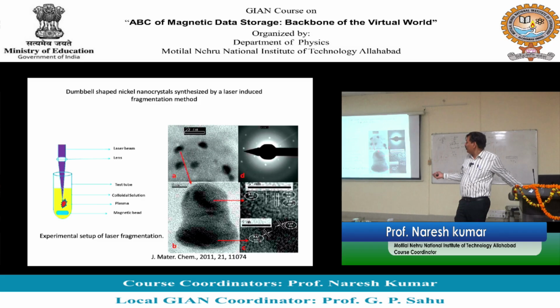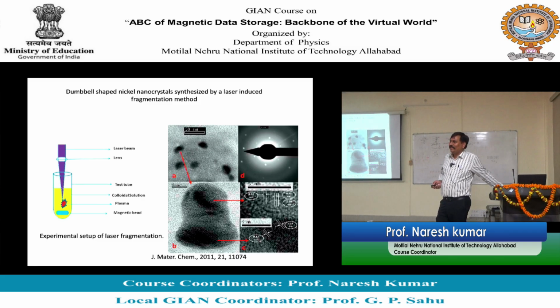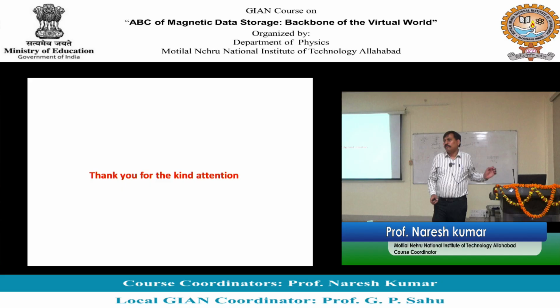But this looks easier than it is. We had a big, just an accident, I would say. The moment you shine light here, it will catch fire. Ablation does not happen here. To prevent fire, we had some inert gas in this localized region, so that oxygen was not available and we could grow the nanoparticles. So you see these dumbbell shape kind of nanostructures of nickel could be grown. So that's all. I would stop here.